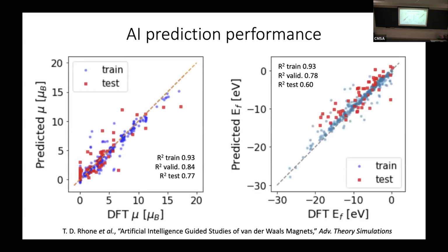So for predictions of formation energy, you pretty much trust those at, let's say, cheap flavors of DFT. If you go to more expensive flavors of DFT, which aren't amenable to high throughput calculations, calculating very many hundreds of materials, you get better accuracy, but you can't do very many calculations. For formation energy, you're pretty much fine. But for predicting magnetic properties, it's notoriously difficult. Sometimes, depending on materials class, it fails entirely, and it just really doesn't work. You have to do more sophisticated things at the very beginning, include on-site interaction parameters for lattice sites to compensate for the approximations of the first principles calculations, and then you start getting reasonable results.